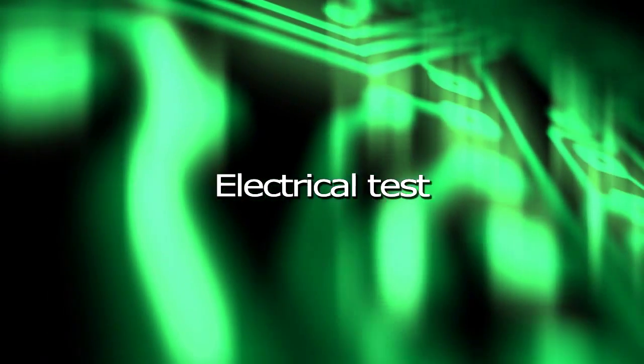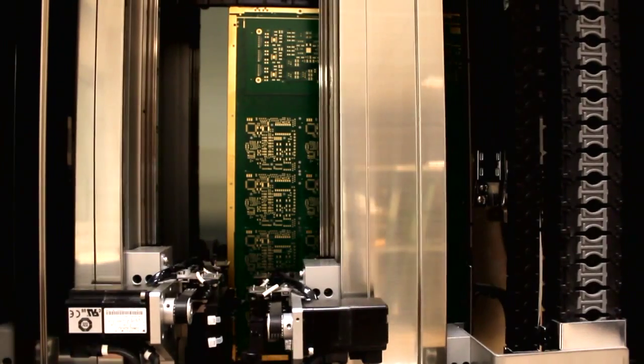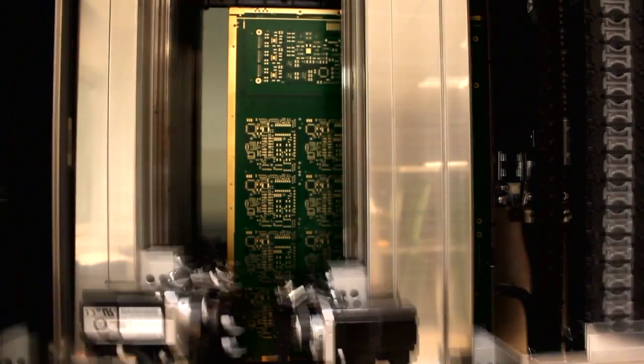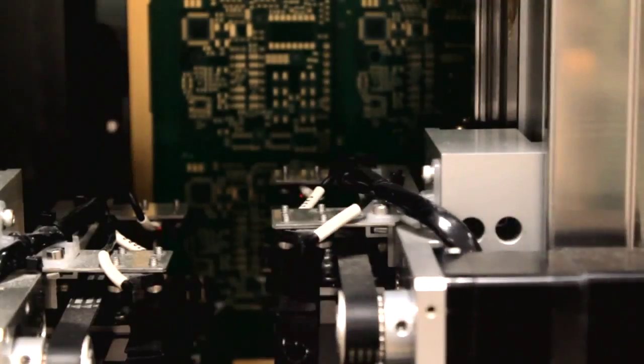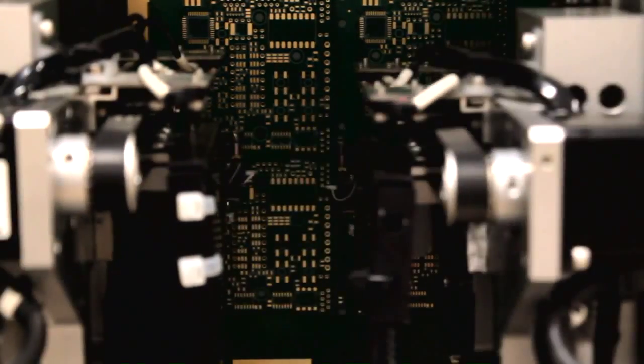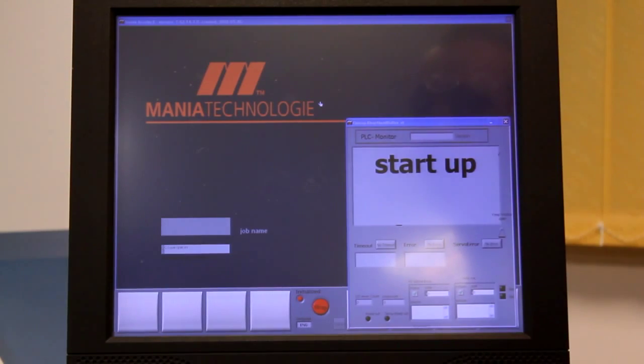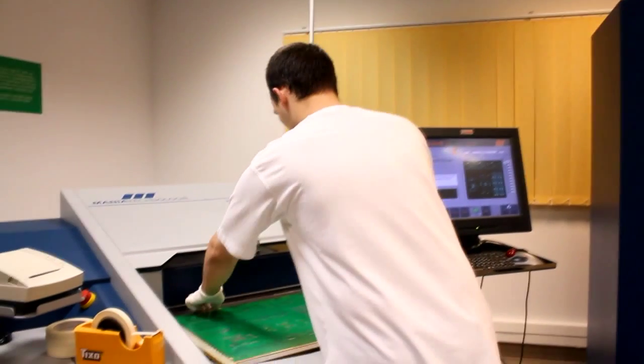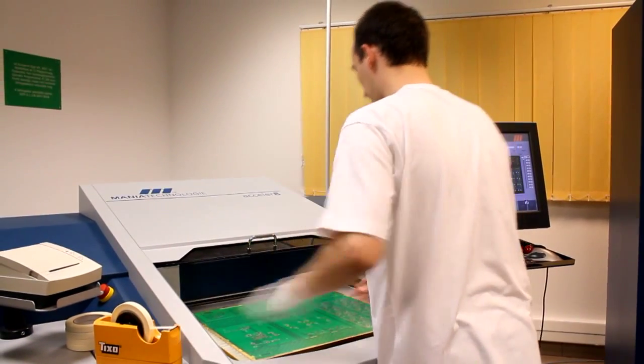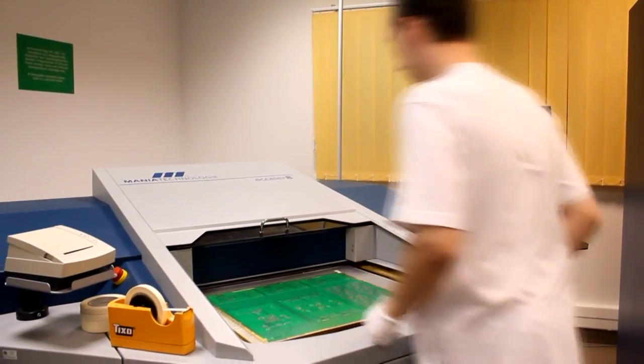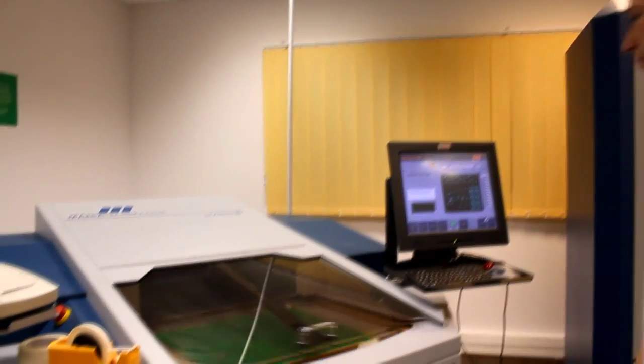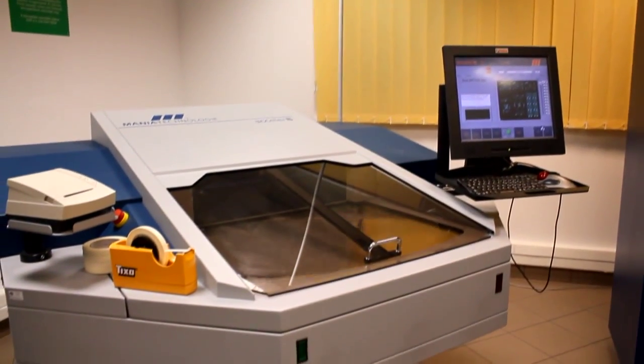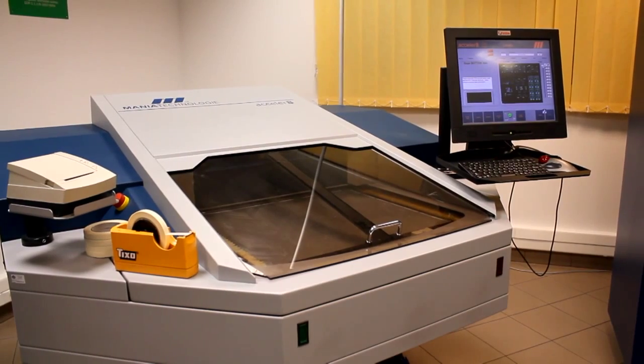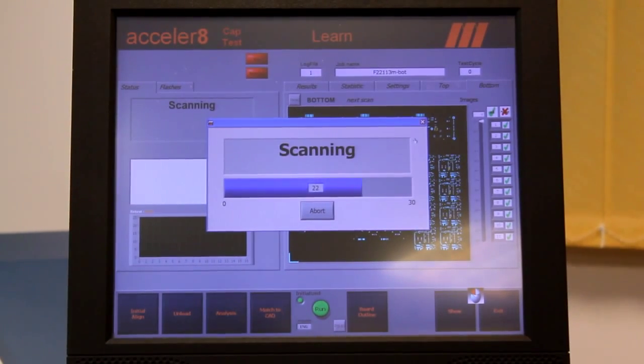Electrical test. Using a flyer probe tester, we check each net to ensure that it is complete, no open circuits, and does not short to any other net. A faster test method is the Acceler 8. This uses 4,000 tiny probes like a brush. It builds an electronic map of the PCB from a pre-tested good board. Then it compares each board to be tested with its map. This cuts test times by 90%.